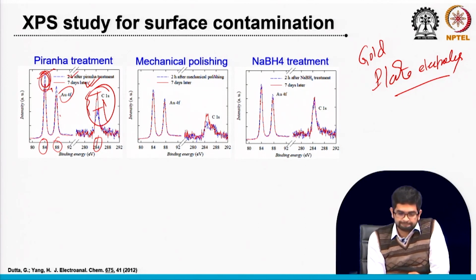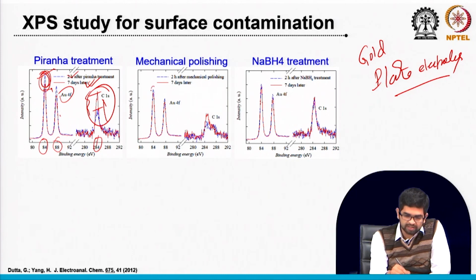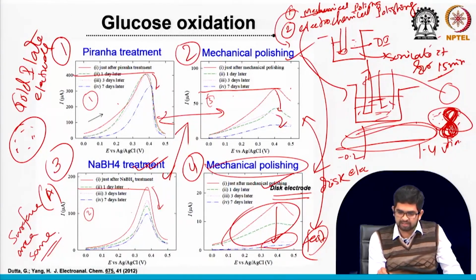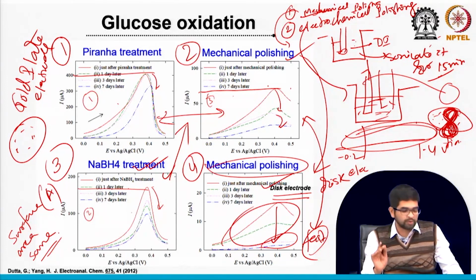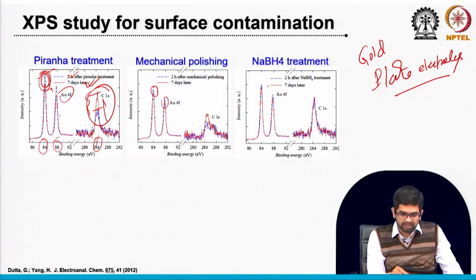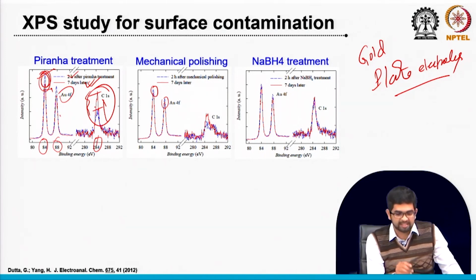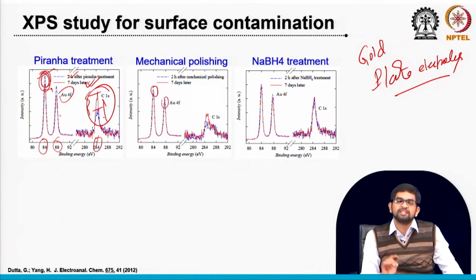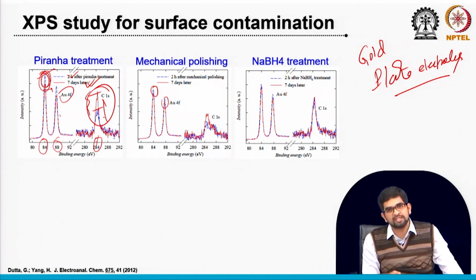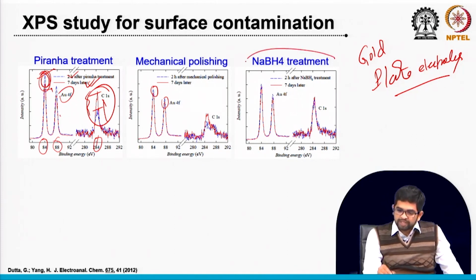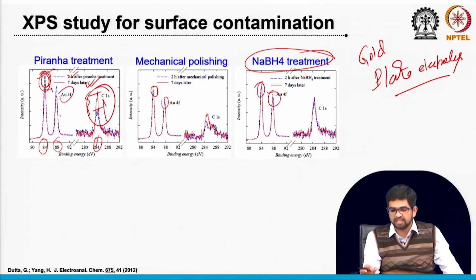Now, check the mechanical polishing case. You see, in the mechanical polishing case we cannot see much change, because as I told you, if you go back, the peak here does not increase that much, also the activity. So maybe the surface is not fully clean just after mechanical polishing, that we can say, right? That is why, if you compare the intensity and the change after 7 days, it is not that much. But in the piranha case, we can see the clear change. Why? Because piranha can almost clean the surface. That is why if there is a little bit of change in the carbon contamination, we can see the change in the X-ray study. But in the sodium borohydride treatment case, we can see the gold peak shows almost no change, and the carbon peak almost no change.